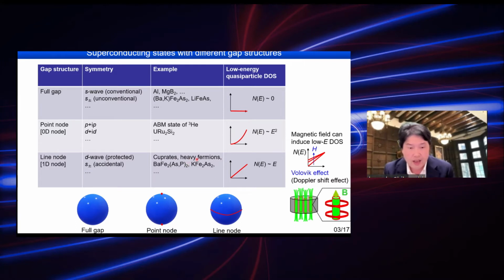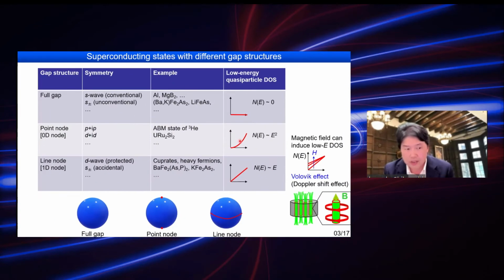In this unconventional superconductivity with nodes in the superconducting gap, the low energy quasi-particle excitations have energy power dependence of energy spectra. And if you apply a magnetic field, what happens is that you create superconducting vortices around which you have the supercurrent flowing like this, which results in the so-called Doppler shift in quasi-particle spectrum. And then you induce the low energy quasi-particle density of states. That is called the Volovik effect.